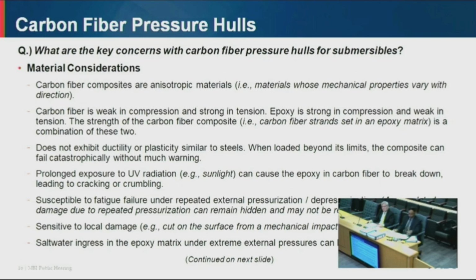Okay, and then saltwater ingress in the epoxy matrix under extreme pressures can lead to delamination. Okay, now epoxy resins in general are highly resistant to saltwater damage. However, if you have voids in the epoxy, okay, we have air pockets, salt water can accumulate in these air pockets, and over time, this can form saltwater crystals. And then over several pressure cycles, this can cause delamination of the pressure hull under extreme pressures. Delamination means separation of the carbon fiber plies. Okay? So that is another damaging effect that is possible in carbon fiber composites. Next slide, please.